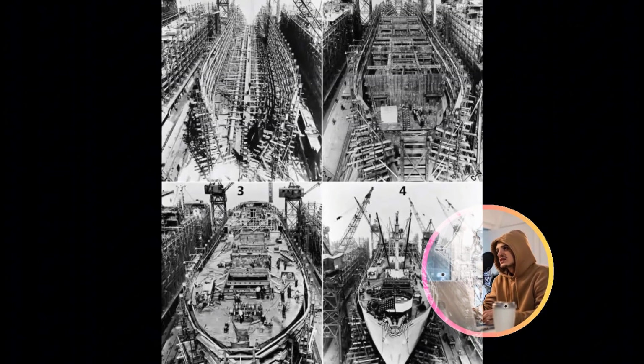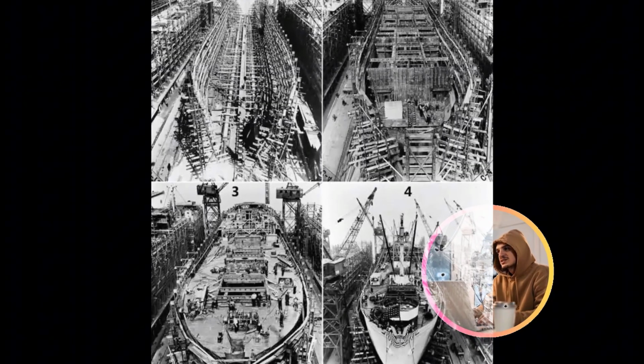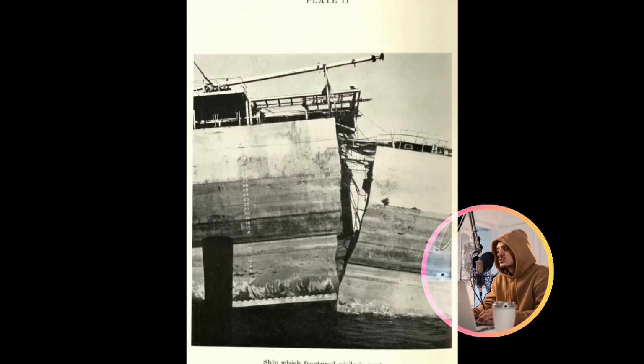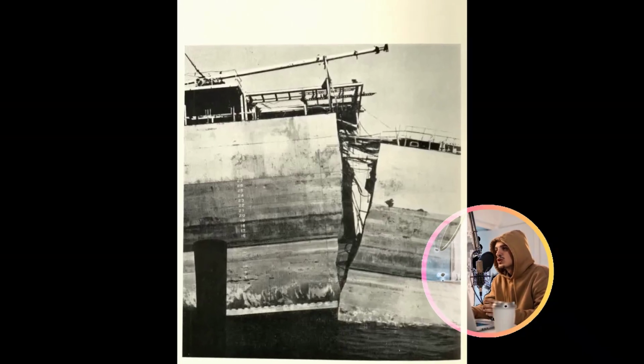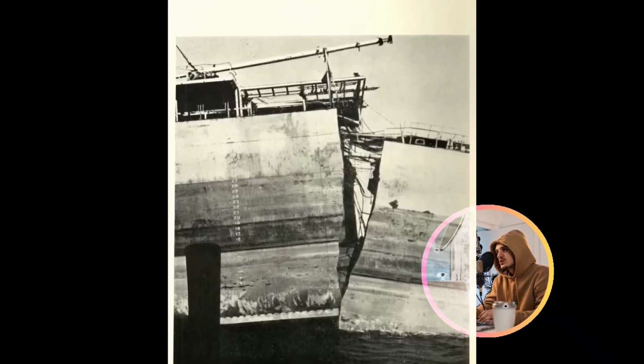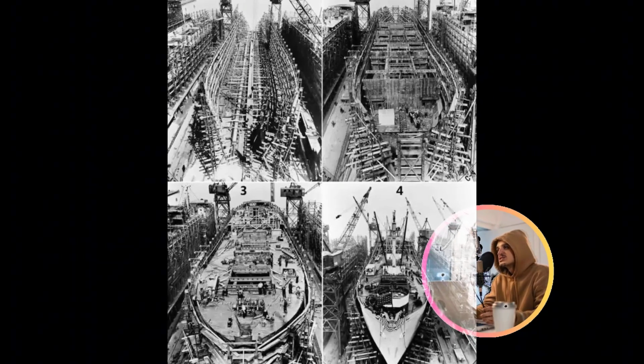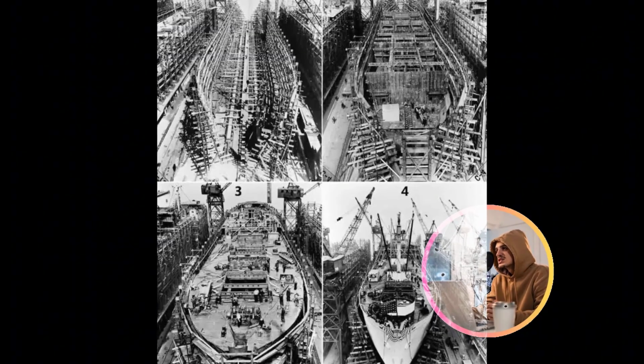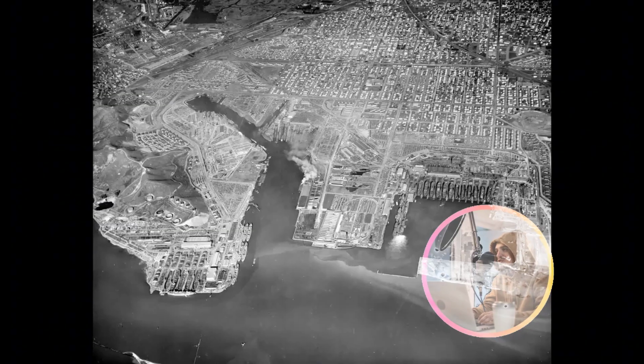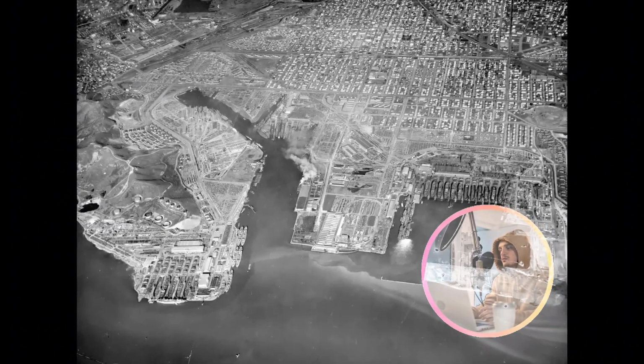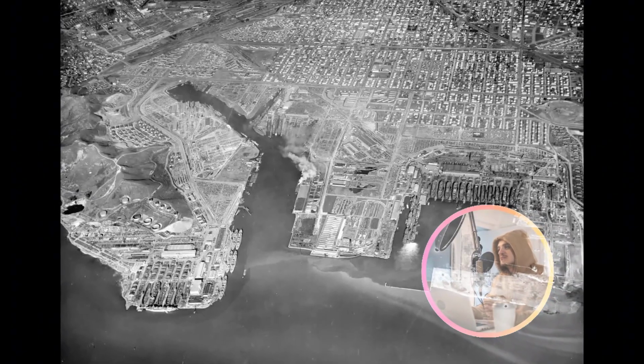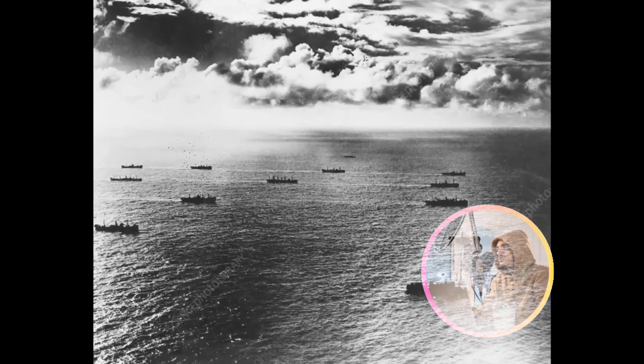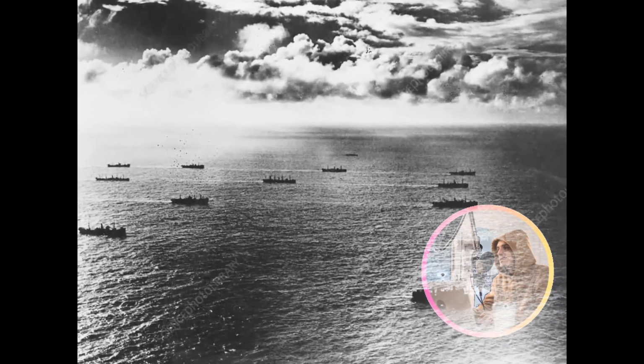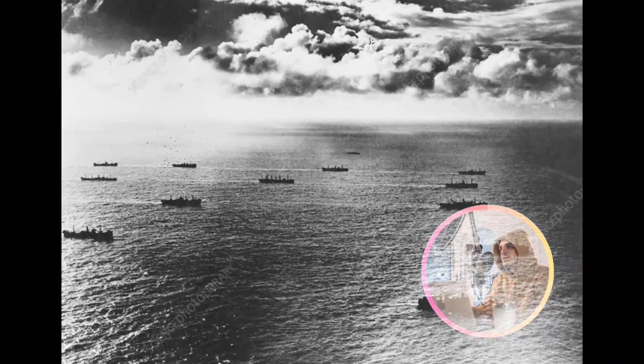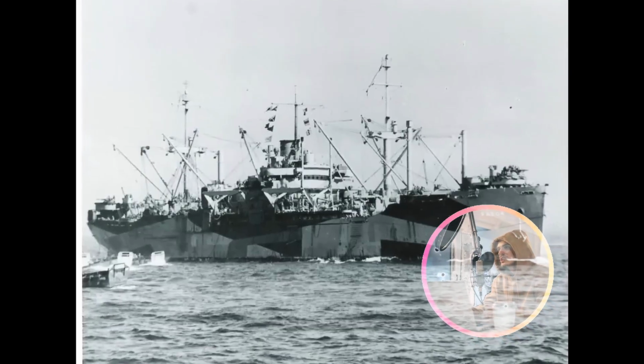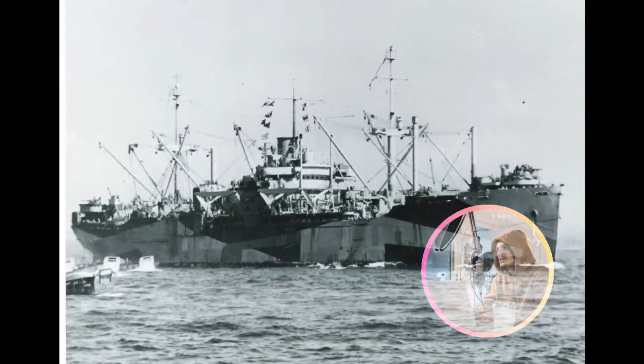Welders received extensive training to diligently monitor the interpass temperature, the precise heat level of the base metal in the interval between consecutive weld passes. If the steel's temperature ever exceeded a critical threshold of 400 degrees, all work was immediately halted, and operations would not resume until the material had naturally cooled. This stringent control effectively prevented the cumulative heat buildup that had been a primary cause of massive distortion in Liberty ship construction, where welders sometimes worked continuously on lengthy seams, superheating the steel into warped, highly stress-riddled configurations.